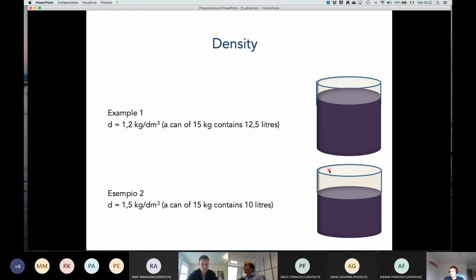It's a real example. These are two adhesives for the application of wood floorings. The density of the first one was 1.2 kilograms per liter, I can say. So this means that a can of 15 kilograms contains 12.5 liters. And a second adhesive from a competitor, again 15 kilograms, so the weight was the same, but the density was higher. It was 1.5 kilograms per cubic decimeter. And if you make the calculation, this means that this can contain 10 liters. So 2.5 liters less than the first one.